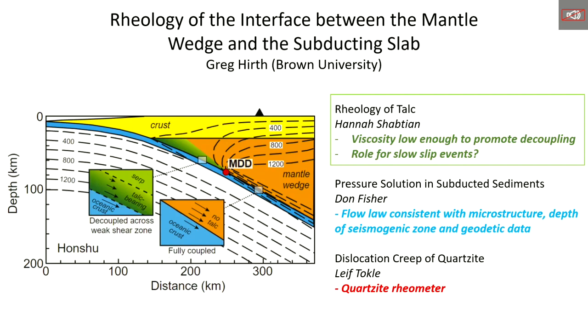It makes us think more about what are the processes that could conceivably accommodate slow slip rates. And I would point right back at me about what about the stress state. But the work that we did with Don on pressure solution suggests pretty good evidence that the stresses down in the 30, 40 kilometer range could easily be 20 megapascals, consistent with the microstructures you see in the rocks.